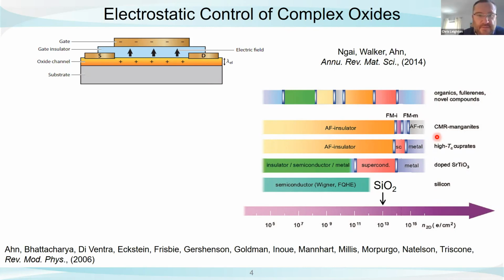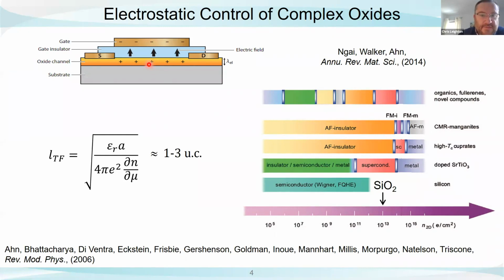The other part of the problem is obviously this doping is a surface effect, an interface effect. These charges hug this interface. How deep do they penetrate? Well, that's controlled by the Thomas Fermi screening length. These materials have much higher electron and hole densities than conventional semiconductors. So this length scale ends up being very short, 1 to 3 unit cells. So if we want or expect a volumetric effect in this film, we're going to need it to be just a handful of unit cells thick, which is going to introduce a whole bunch of other challenges, okay?